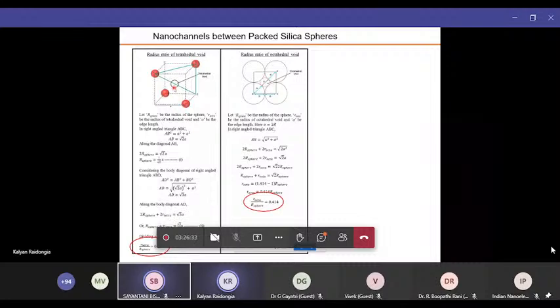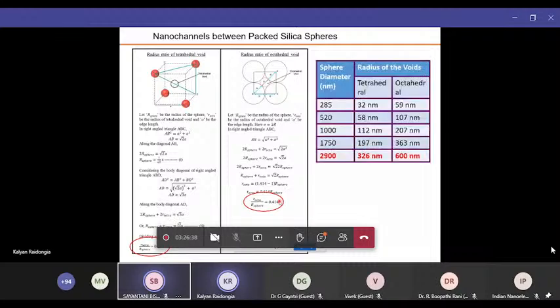For tetrahedral holes, it is 0.225, and for octahedral 0.414. Then we can find out from that, we use mostly DI water, which can be considered as 10 to the minus 6 molar concentration. So Debye length we can calculate to be around 300 nanometer. Then we can see this around 1750 nanometer size pores.